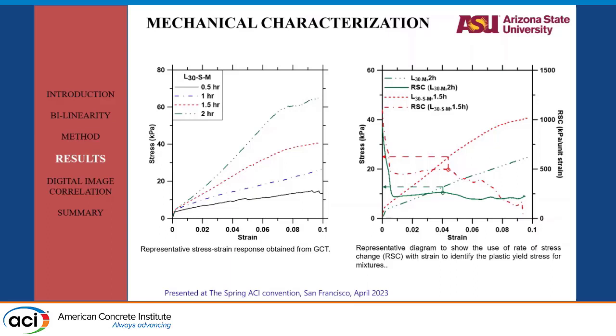Second thing that was important was the plastic yield stress. What is plastic yield stress? You could keep on loading the cylinder. It's an engineering stress strain graph. So for the engineering stress strain graph, we saw that it kept on increasing. So we needed a point at which we could say, okay, this most probably is the plastic yield. For that, we did a modulus check. So basically a slope check, where wherever the modulus started drastically dropping was our plastic yield stress.